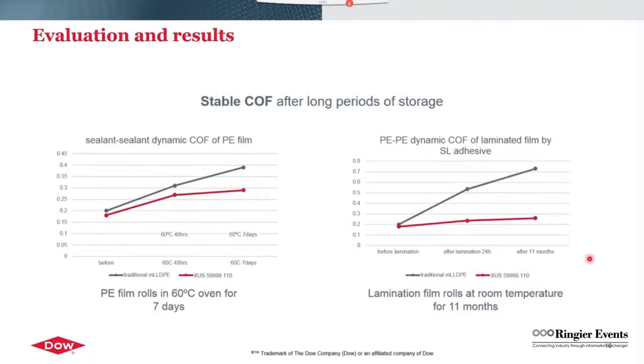The graph on the right-hand side shows the COF of the lamination film with solventless adhesive after storage for 24 hours and 11 months at room temperature. With the traditional metallocene LLDPE sealant, the COF increased to 0.5 after 24 hours of storage and to above 0.7 after 11 months. While with the COF stable resin XUS 59900.110, the COF was maintained below 0.3. This demonstrates that the COF stable resin XUS 59900.110 can help to maintain low and stable COF of the packaging film even if it needs to go through long time storage or transportation.